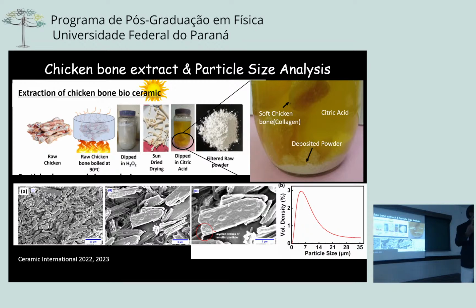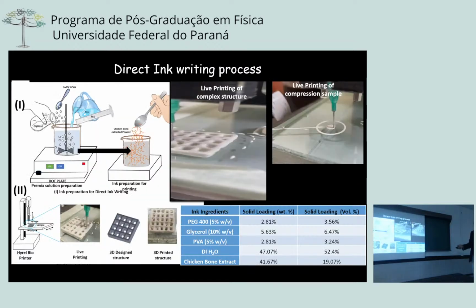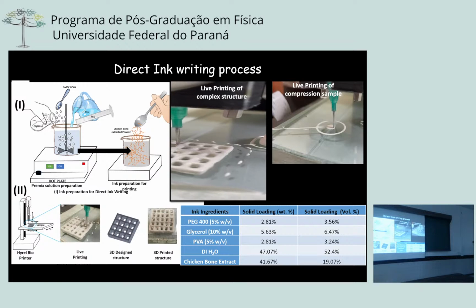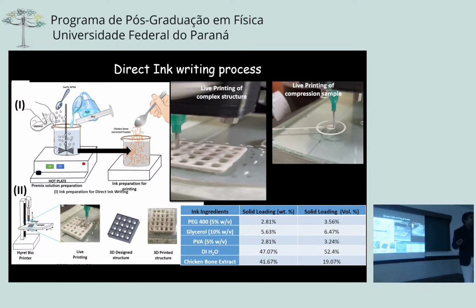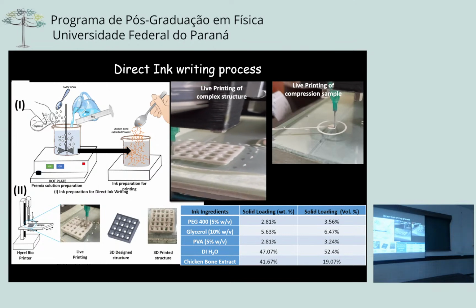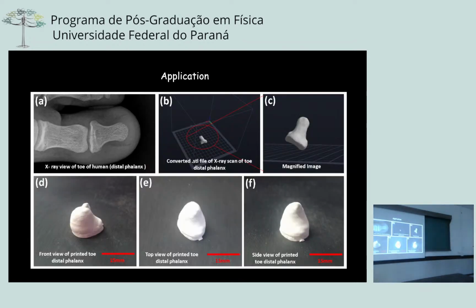The chicken bone is made of two different materials. One is organic, collagen, the other is ceramic. Now what the chemical treatment does is etch out the ceramic particle, right? So what you are doing is you are creating a bone from a natural bone material, right? And if you look at this powder in AFM, they are small particles of 5 micron lateral dimension and 10 nanometer thickness, almost like 2D materials. Now what is the advantage if you have this kind of morphology? It's easy to make ink out of it because they can slide on top of each other. We take this material, put in the right rheology, and then you can print them. Because of this nature or geometrical aspect, we can nicely align them. And if you do that, you can control its mechanical properties and you can print with a very high resolution.